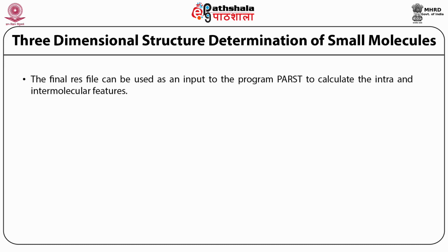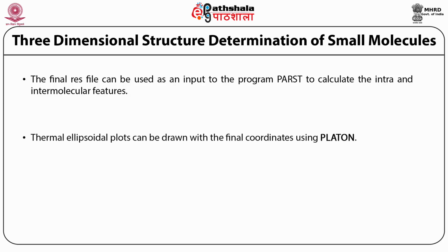Once you have everything done, the final res file can be used as input to the program written by Professor Nardelli called PARST to calculate the intramolecular and intermolecular features. By intramolecular features, I mean bond lengths, bond angles, torsion angles. By intermolecular features, I mean hydrogen bonds between the symmetry related molecules and so on. Again, the final thermal plots can also be done using PLATON. With these results, one can submit the research findings as a publication to the crystallographic journals.